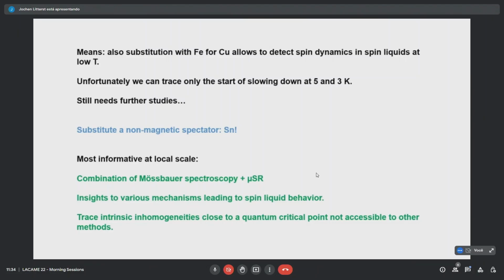And we can directly see from transferred fields how the correlations are developing. To summarize, I think on local scale, it is really a good combination to look at Mössbauer spectroscopy together with muSR on the same samples. We can have insights, especially into the mechanisms which lead to very different kinds of spin liquid behavior, as we had shown before, for these classical spin liquids or the orbital spin liquids, and now also on the quantum spin liquids.